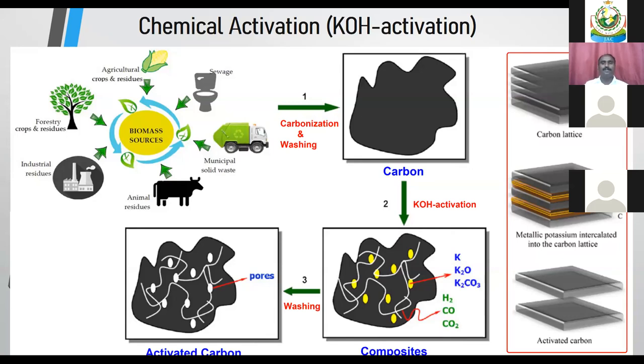So this is the carbon lattice. This is a bare carbon lattice. There is no porosity, there is an intercalation. After mixing with this potassium hydroxide, the potassium is intercalated between these two layers of the carbon lattice. And after washing out this potassium hydroxide, we get the porosity, that is the activated carbon. So this carbon is used for further applications.